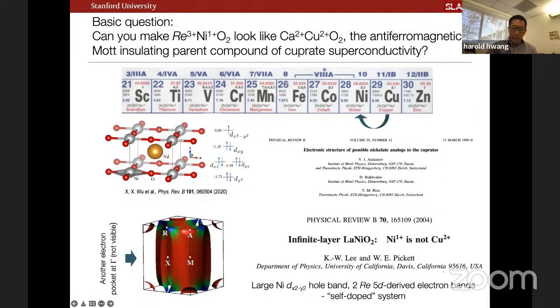And subsequently, Warren Pickett and Lee pointed out an important feature that we'll come back to here and there in the discussion, which is that this is not a complete analogy, in the sense that there are big qualitative differences in the electronic structure. In the LDA limit, for example, what they find, and this is pretty much the consensus of quite a few more electronic structure calculations, is that you have a cuprate-like large Fermi surface of dx²−y² character. But in addition, you have these electron pockets.